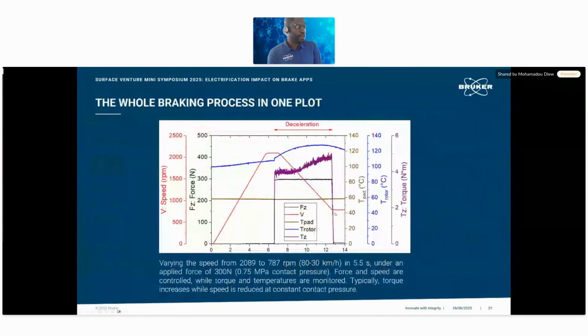After the test, you will get on one plot all the parameters that you can control on the system. It means the speed, the load that you apply. You can also measure the temperature of the pad, on the backside of the pad, even though the pad can sometimes be insulating material because it's a composite. The rotor disc with a sliding thermocouple, and you can also measure the torque that you get at the system. It means during the braking event, you can get all of this information.